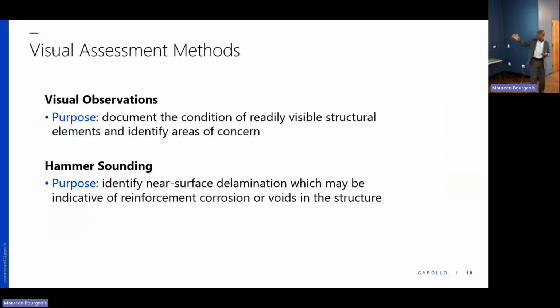And so based on that, we also did hammer sounding. We basically take a hammer and hit the structure, knock it around. If you think about something solid, when you knock it, you get a distinct sound. But if there's a void behind it or if it's hollow, the sound will also show up. And so you're able to detect those two different sound conditions, and you can tell whether a structure is sound